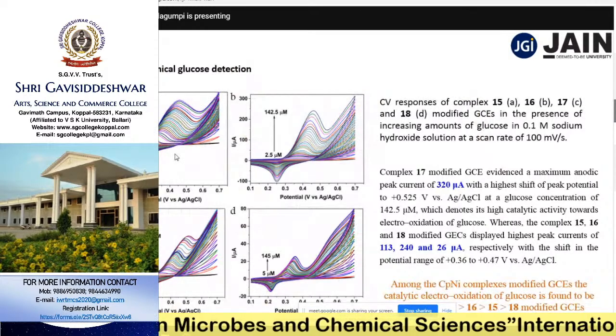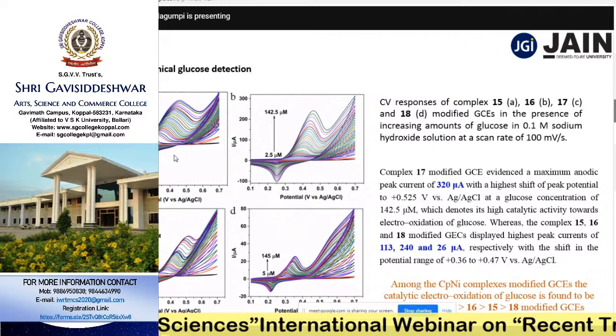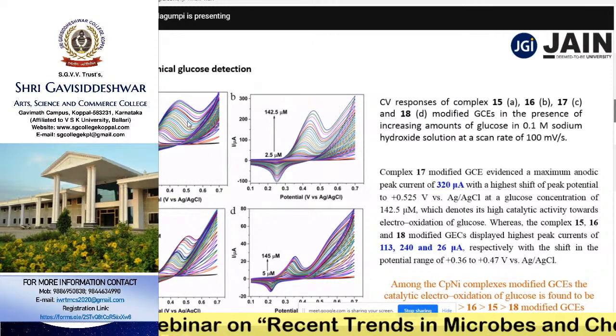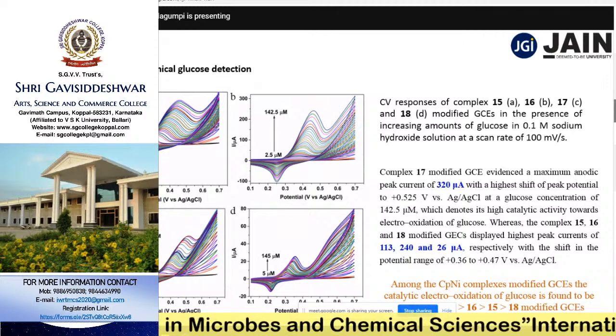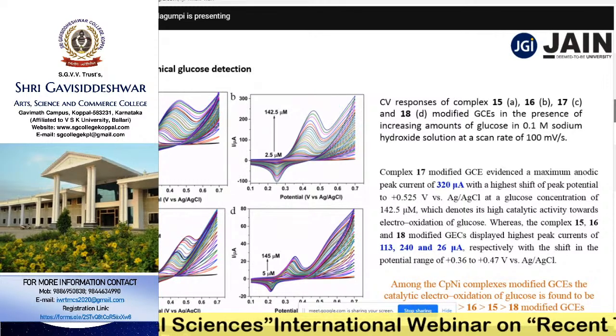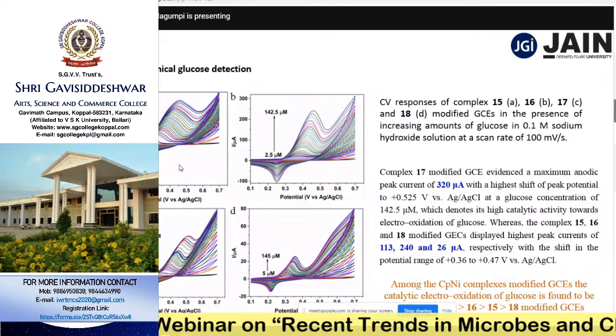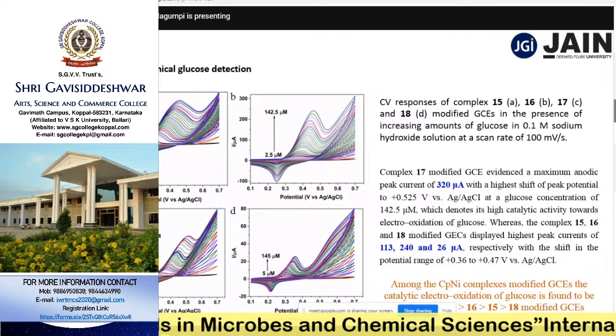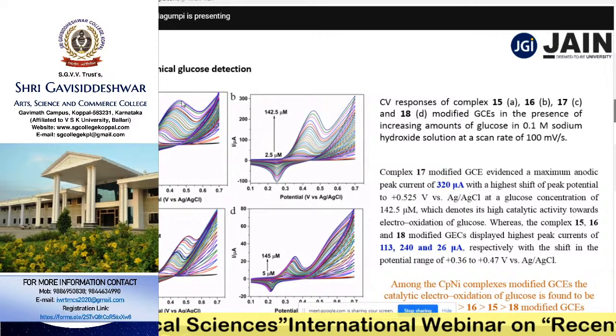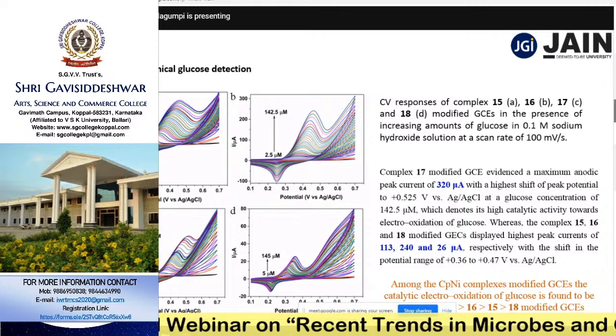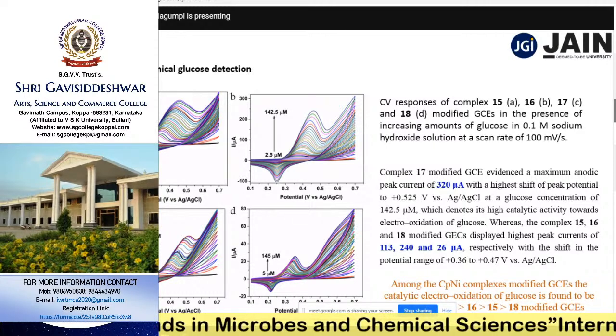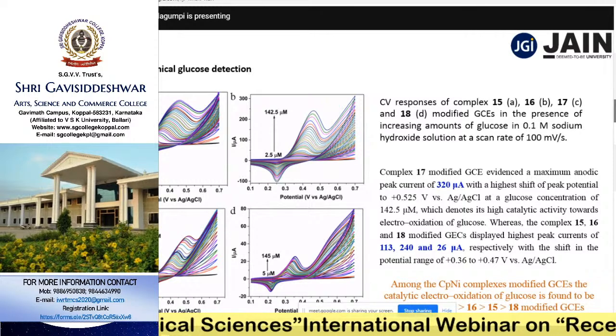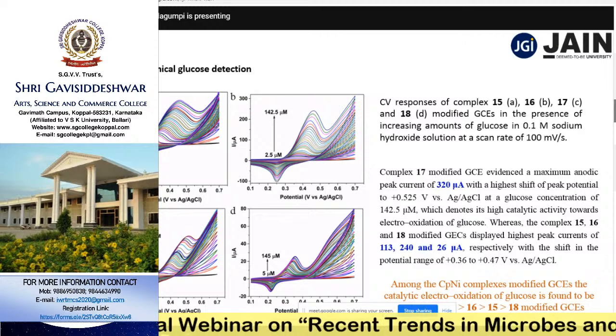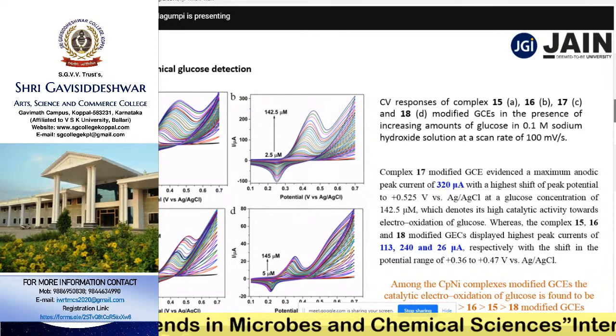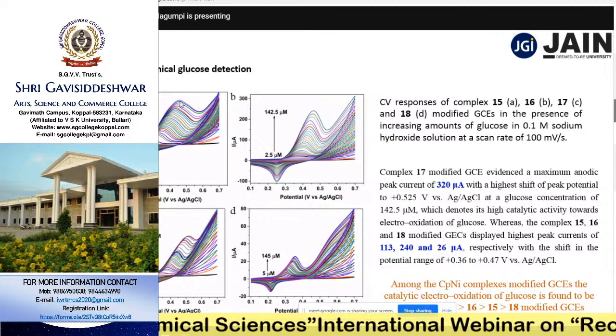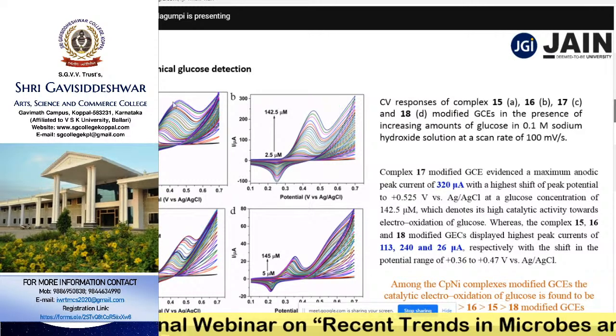So with that 3 electrode assembly, the complex-modified working glassy carbon electrode, the Ag/AgCl electrode, and the platinum electrode. In the electrolytic solution, the red one, there is no glucose content. It is just sodium hydroxide solution. As the glucose concentration was increased in the electrolytic cell, the peak currents, the oxidation peak currents corresponding to nickel, have increased. For example, here we could hardly find 10 microamps of current in the absence of glucose, while upon addition of 142.5 micromoles of glucose, the current was increased more than 10 times. We could get more than 100 microamps of current here.